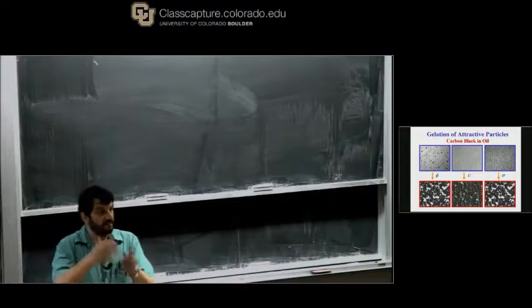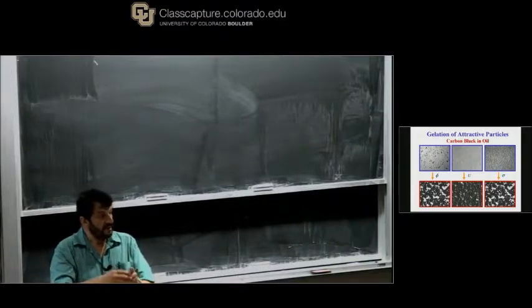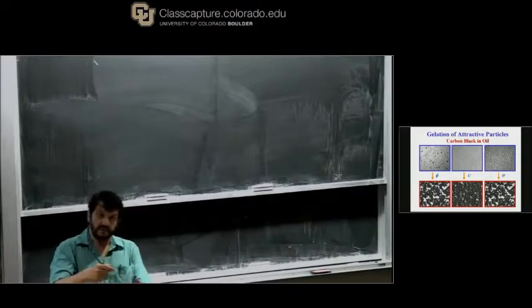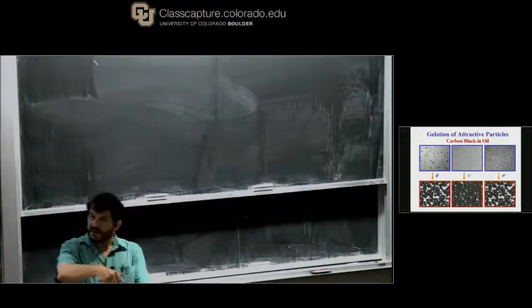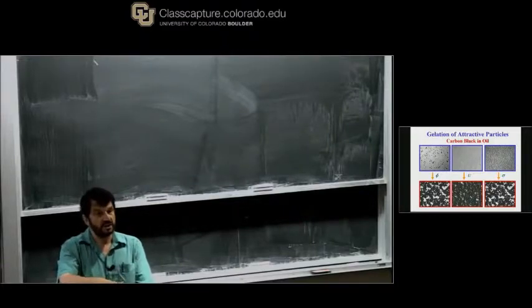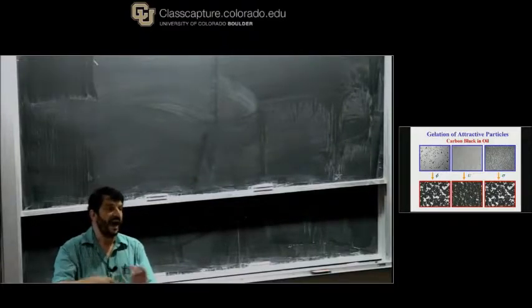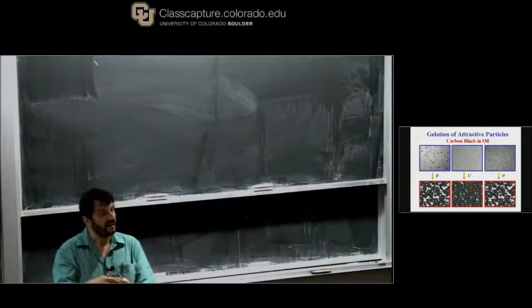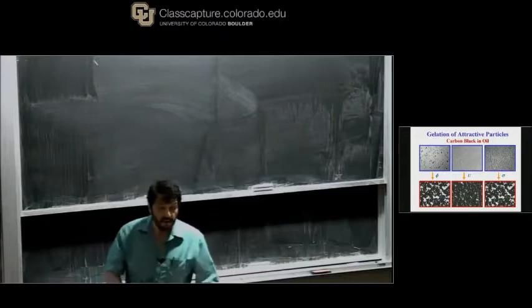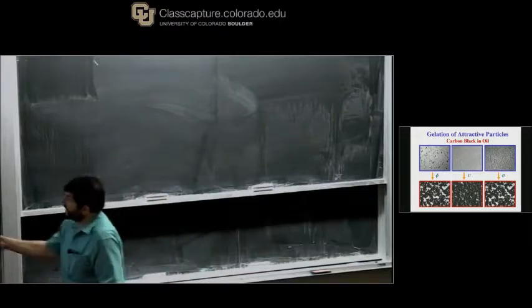And one of the things is it produces soot in the diesel oil, in the diesel fuel. And soot is like little carbon particles, little colloidal particles. It grows. How does it grow? It grows as a fractal. And what it does is it changes the viscosity of the oil. So they asked us, please, can we understand how to think about that? And basically, we showed that these things basically gel because they form these fractal clusters. And this is what it looks like.